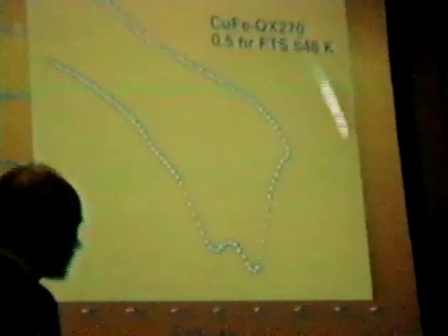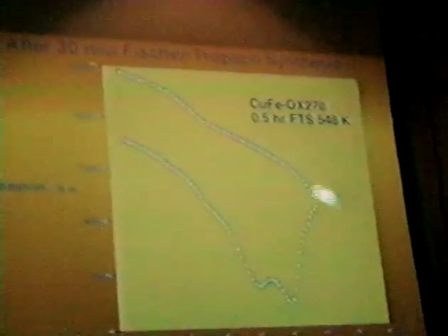And you can see from our magnetic work whether we succeeded in preventing the formation of carbide, and we didn't succeed at all. You get a very rapid segregation of iron carbide from the iron-copper alloy. So again, you can see after half an hour of Fischer-Tropsch synthesis, there is the carbide, the ferromagnetic carbide. Here we get a tremendous decomposition. So this is a highly active catalyst. We have a lot of a very unstable carbide which is easy to decompose.